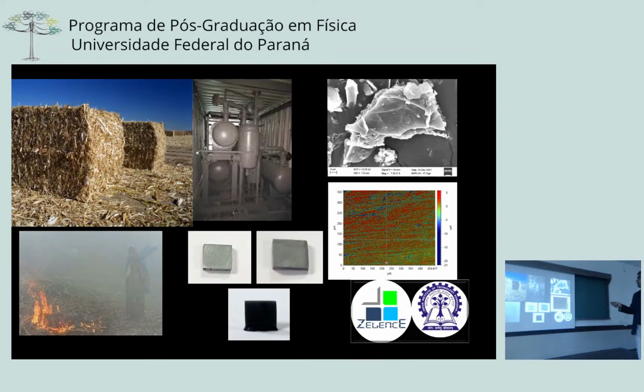And so we built this setup where we treat the agriculture waste, put them under a simple chemical treatment and thermal treatment, and what you see here is nice layered carbon. It's a mixture of amorphous and crystalline carbon with a small amount of silicon. Now if you have that, you can use this nice green graphene, we call it. We can coat on different substrates.